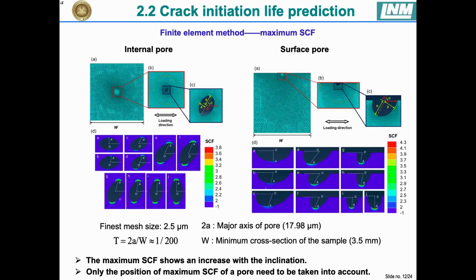For the maximum stress concentration, the finite element method is applied in this model. The inclination means the angle between the major axes of the pore and the loading direction. It can be seen from the simulated results that the maximum stress concentration shows an increase with the inclination, and only the position of the maximum stress concentration factor of a pore needs to be taken into account.